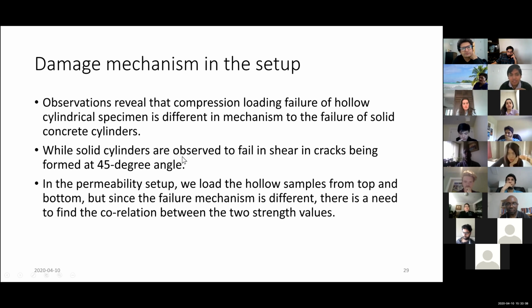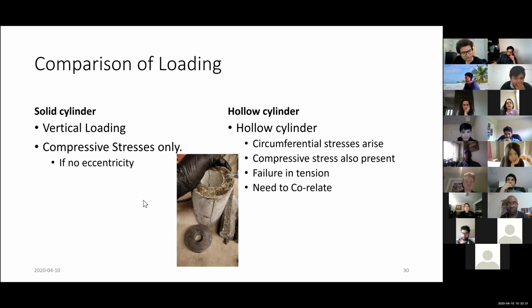So in a solid cylinder, we usually observe a shear crack at a 45-degree angle. So there is a conical failure, as you might all know. And in this permeability setup, we load the hollow samples from the top, but the failure mechanism that I found was slightly different. And there is a need to find the correlation between these two values, which I am struggling currently how to correlate these two.